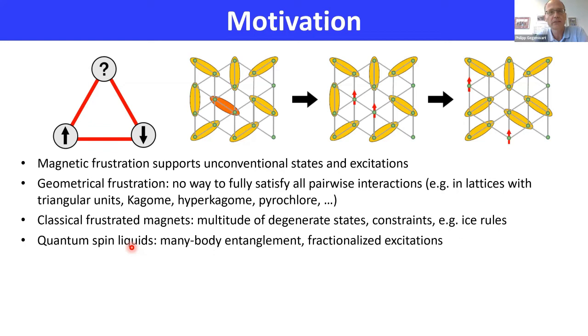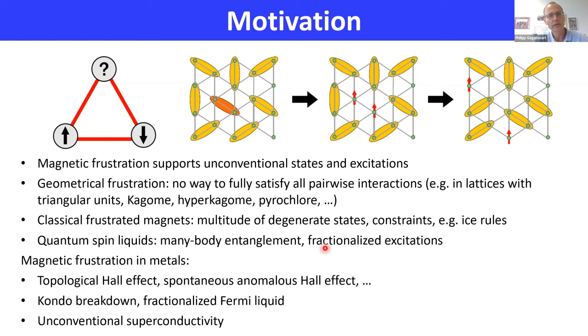All right, so the motivation to look for magnetic frustration is, of course, that it supports unconventional states and excitations. We define geometrical magnetic frustration as a situation where we cannot fully satisfy all the different pairwise interactions, and that leads to interesting new phenomena. If we just consider classical spins, then we can typically have some constraints which define the ground state and which lead to a multitude of degenerate states at the lowest energy, like in the spin ice cases. And if we also consider quantum mechanical effects, it's getting more interesting, because then many-body entanglement and fractionalized excitations may become visible.